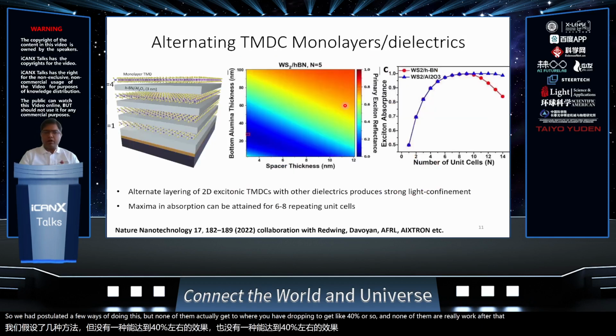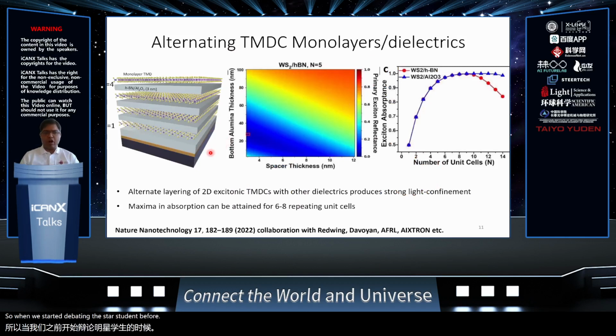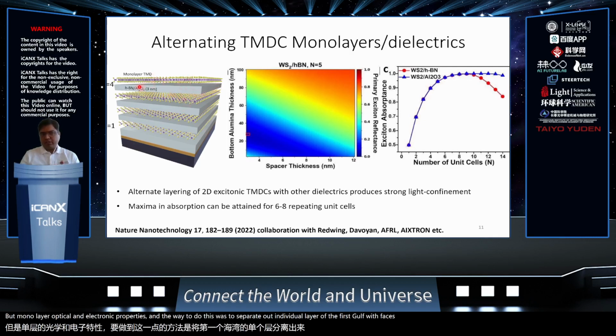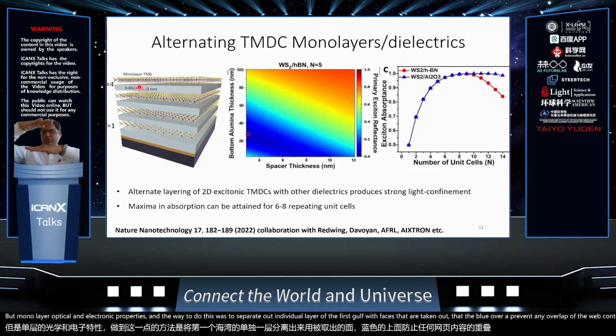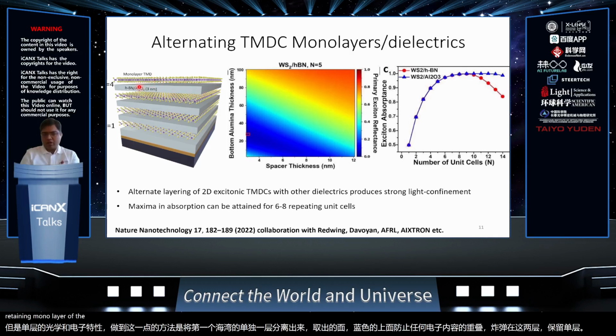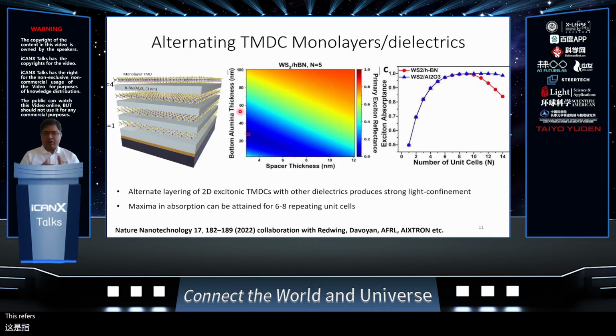So when we started debating this with our students, we found that the one way to do this would be to maintain multi-layer structure, but monolayer optical and electronic properties. And the way to do this was to separate out individual layers of these crystals with spacers that are thick enough that will prevent any overlap of the wave function of electrons or excitons in these two layers, retaining monolayer optical and electronic properties.